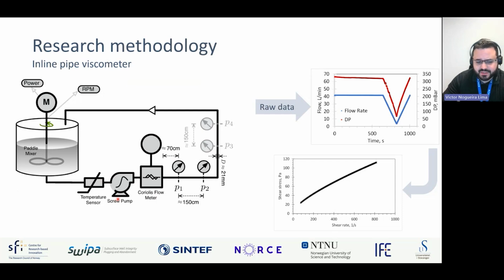Also a screw pump. This screw pump is a very good feature because we can ensure that we have the flow without any pulsation effects. So we can ensure that you have this smooth curve when reading the flow measurement and also the DP, and also a temperature sensor. So we can make sure that all the variations that we read when it comes to pressure variations are related to temperature rather than variations in the slurry properties by itself.